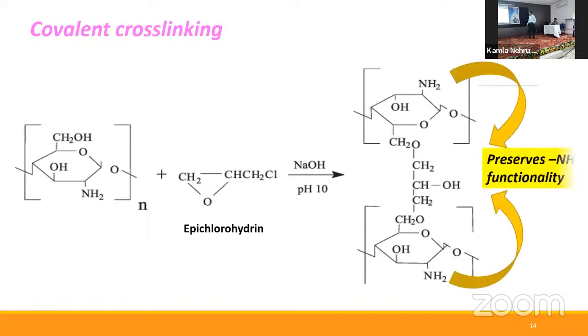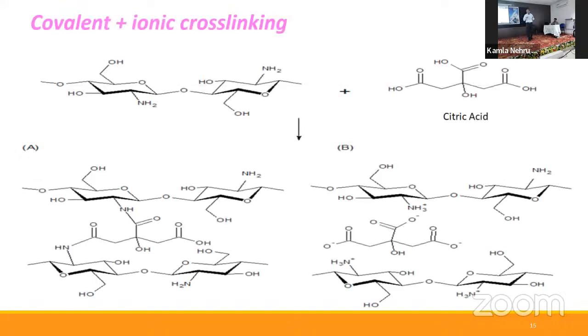Another way of carrying out the cross-linking is better than that. That is, the epichlorohydrin can be used as a cross-linking agent, which does not cross-link to the NH2 group, but cross-link to the OH groups, and as a result, this NH2 functionality is preserved. So there is another way of cross-linking chitosan. There is a possibility we can use some say polycarboxylic acids. So we can have a combination of both covalent cross-linking as well as ionic cross-linking.